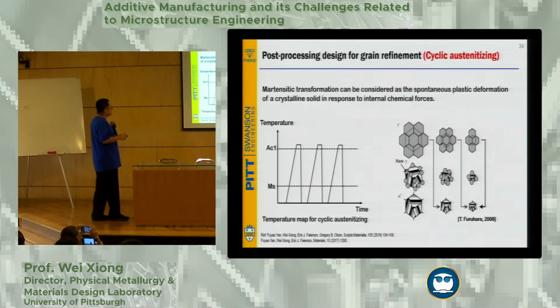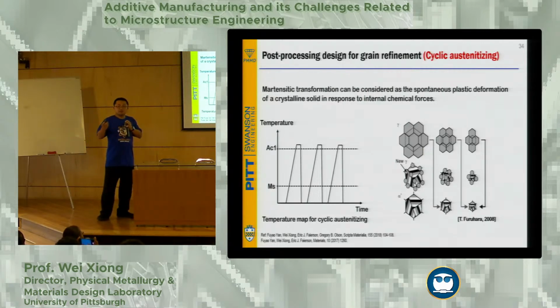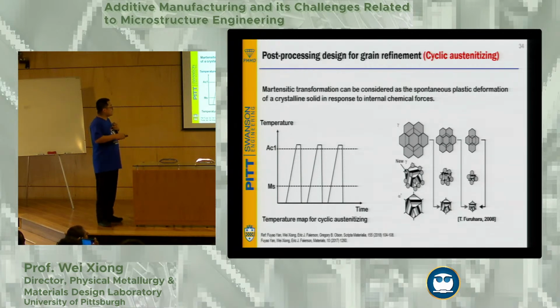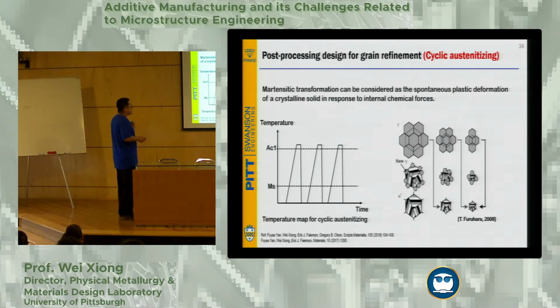Once you form the new martensite, you'll have more nucleation sites, more dislocation density, and therefore much finer grain size. That's the well-known technique, the cyclic austenization process.